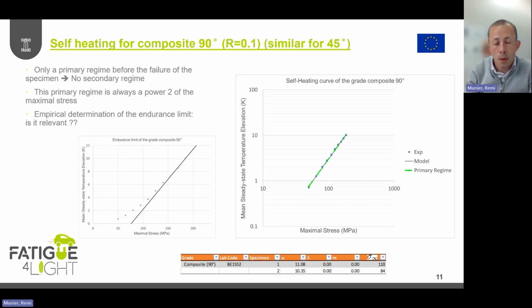I have shown before that the temperature evolution could be a contribution of two regimes. For composite materials, only one is observed. It's always a power of 2 of the maximal stress according to self-heating measurements. But as for metallic materials, we said, okay, why not use the same deterministic approach to determine what could be considered as an endurance limit, just dedicated to the progressive appearance of the temperature.